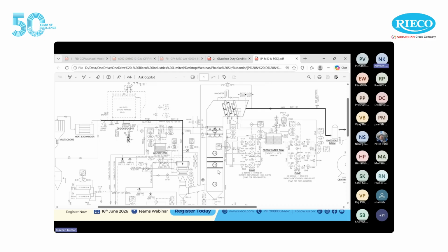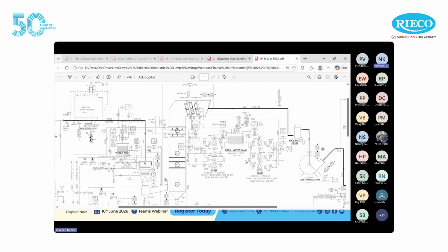At the end of the gas absorber at the top, we can see mist eliminators for taking care of the vapor droplets. And below the mist eliminators, we can see the spray banks from where the lime slurry is sprayed in the gas absorber. Below the spray banks we have what we call pipe decks, which are basically used to straighten out the gas which enters the gas absorber and ensure a uniform distribution inside the cross section of the gas absorber. It also plays a role in enhancing the neutralization of sulfur dioxide.